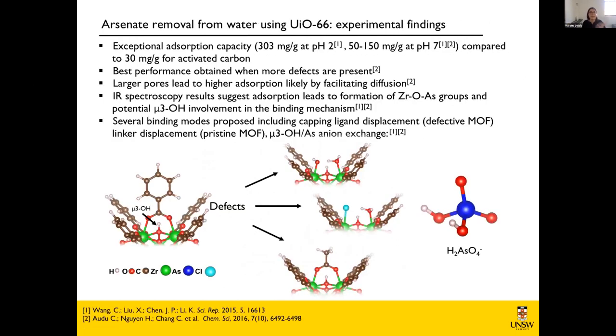Now, there are a few reports, like I mentioned, in the literature showing that UiO-66 can effectively be used to remove arsenic from water. And the performance is quite outstanding. In fact, at low pH, it has been shown that it can get more than an order of magnitude more arsenic out of water relative to what activated carbon would do. And the performance is still quite good, even at neutral pH.